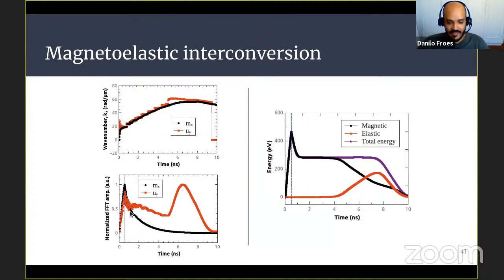Here on the Fourier transform amplitude, you can see that as we are exciting, both of them peak, but the elastic one has a very small amplitude. Here it's normalized, but it's a very small amplitude. But when you get to this point where you have this jump of wave number, the elastic amplitude just goes up. It's not what we would expect if you didn't have this interconversion. So this is an indication that there was a conversion to elastic modes.